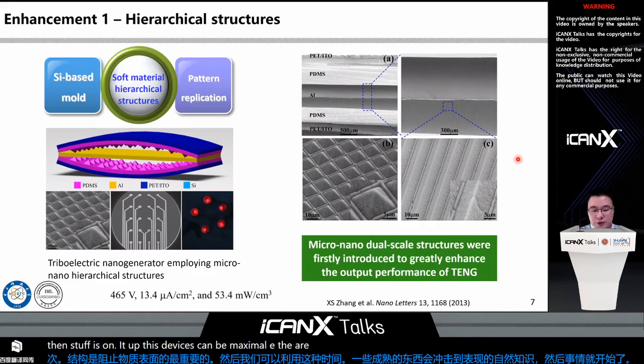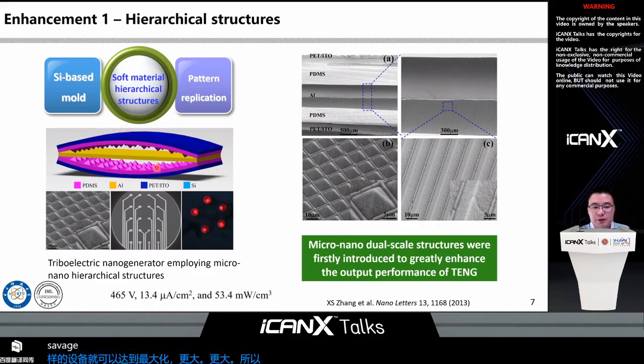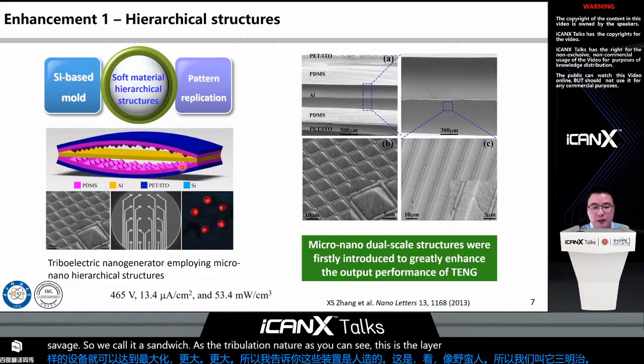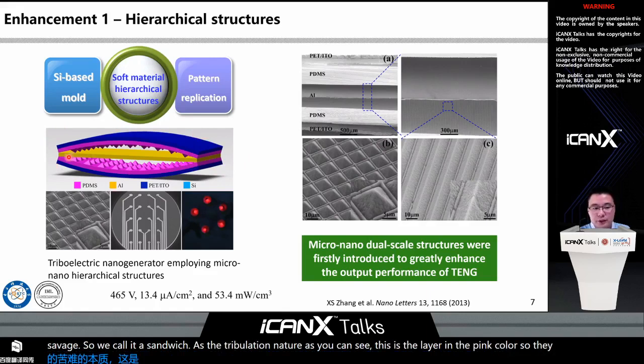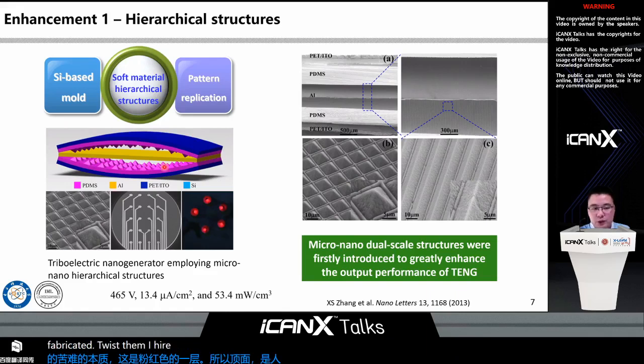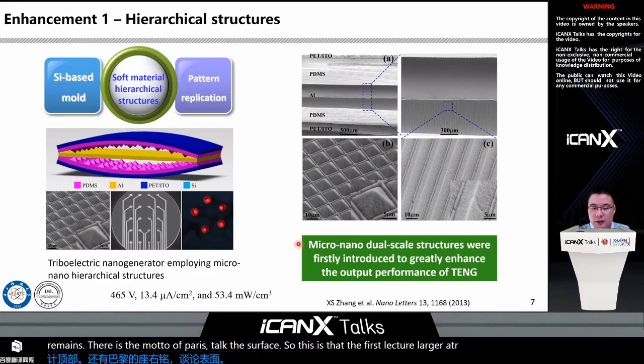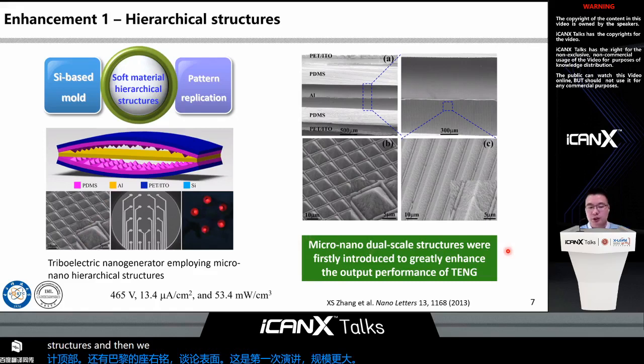So I show you that the device we fabricated here looks like a sandwich. So we call it a sandwich-shaped triboelectric nanogenerator. As you can see, this is the layer in the pink color. Atop the surface, it was fabricated with the micro-nano hierarchical structures. For the microstructures, there are the pyramid arrays, and then atop the pyramid arrays, there is the nanoporous structure atop the surface. So this is the first triboelectric nanogenerator that employed the micro-nano dual-scale structures, and then we can greatly enhance the output performance of the triboelectric nanogenerator.